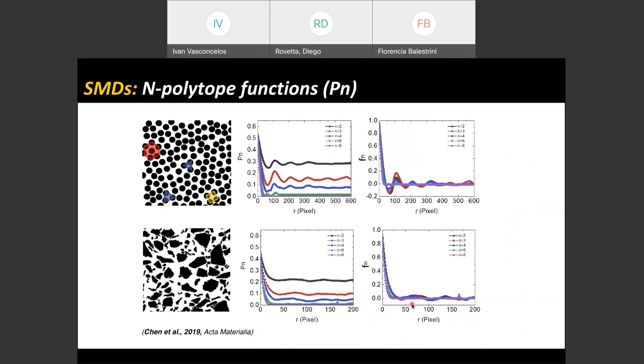Now, if we look at other examples here, now we see impenetrable spheres. You can think of, for example, glass beads are very commonly used in experiments. And you can see here in black the two-point correlation function. And in other colors, you see other polytopes. N3 means a triangle, 4 a square, 6 a hexagon, 8 an octagon. You can see here these other curves. I'll tell you what they are in a minute. And at the bottom, we again see the Fontainebleau sandstone. And you can see that the Fontainebleau sandstone does not oscillate as much as the spheres. That's because it's less self-correlated, which means this material is genuinely more random than the glass beads would be, for example.